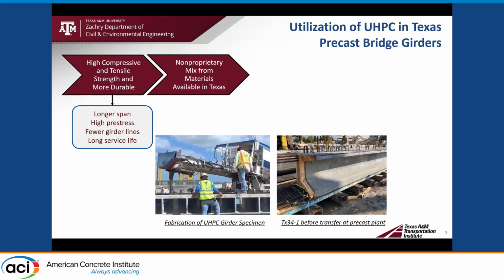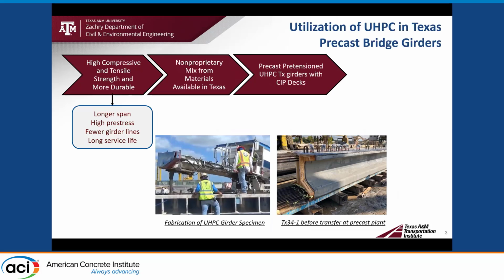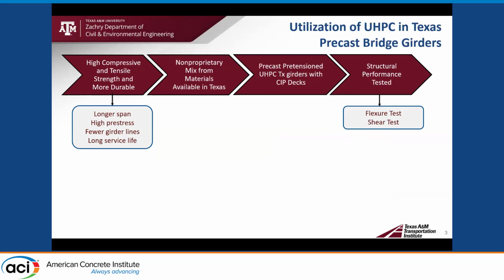We developed a non-proprietary UHPC from locally sourced materials in Texas. This effort was led by my project mate, Young-Ki Hong. And since commercial UHPC is very expensive, it was necessary to develop a locally sourced material mix design so that the cost can be cut down. We tested that developed mix in the precast plant. And once we were happy with the trial batch, we then fabricated UHPC girders at a full-scale level, and we had cast-in-place deck slab poured on top of it in the laboratory. We then tested the performance of these specimens in the lab under flexure and shear.